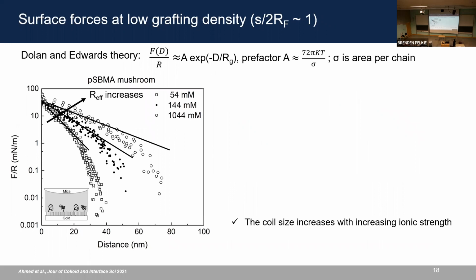Then we also looked at surface forces at low grafting density, and the force distance profiles for the three salt concentrations are plotted on the same graph. And here we see a qualitatively different behavior. At the smaller separation distances, the surface force decreased exponentially with distance, and we can fit the exponential behavior and determine the decay length, which gives us the effective radius of the polymer chain.